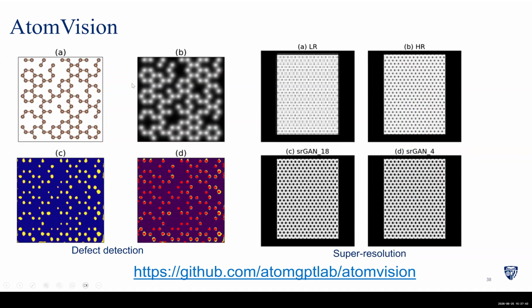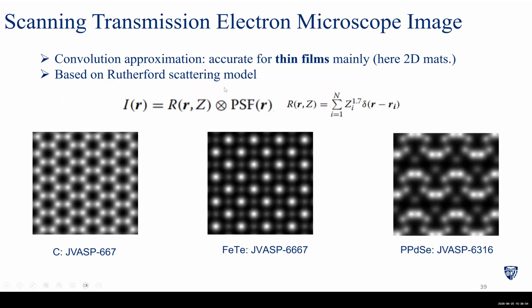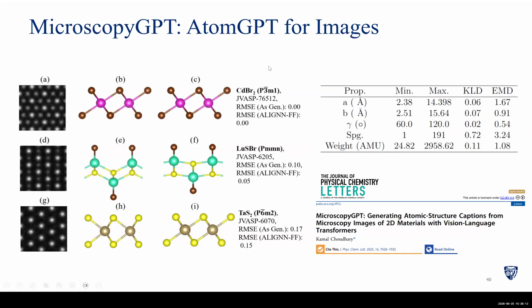So one of the ways to generate the images is using the Rutherford model, where we say the image intensity is proportional to Z squared, or atomic number squared. But of course, instead of the square, we put 1.7 because we have some loss. So we generated such a dataset for perfect materials using this Rutherford model. These are for graphene, iron telluride, and so on. You can see 1.7. And we took this dataset to train a GPT model. So this is called the Microscopy GPT model. Suppose you have an image and a caption. The visual language model, or VLM, when given an image, will try to generate the atomic structure. So similar to the diffraction pattern where we have a diffraction pattern and a CIF file, here we have image to atomic structure. And we found that even for the test dataset, which it had not seen, it did a reasonably accurate job, which was very promising.